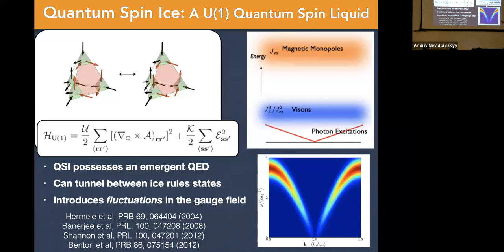So the gapless photons disperse linearly, and they also have some very interesting spectroscopic properties. The most spectacular of these, which is theoretically predicted and has not been observed, is that the spectral weight actually decreases as you go down in energy and vanishes at the zone center. This is similar to the spectral properties of acoustic phonons, but exactly the opposite. Phonons are strongest as you go to lower energies, and their intensity diverges as you get to the zone center. So interesting similarities and differences.